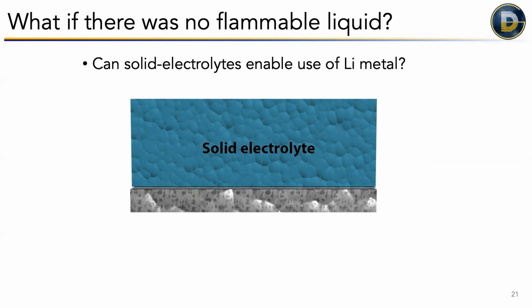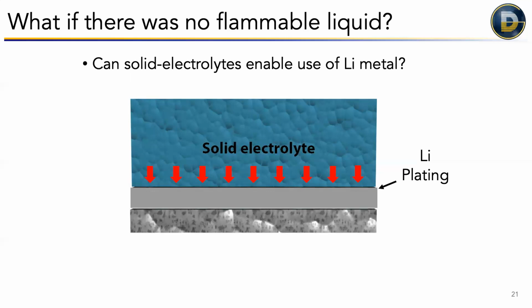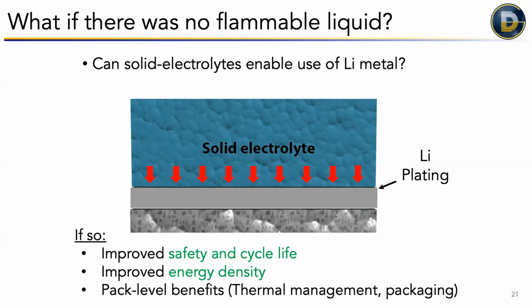But if we can use solid electrolytes to enable the safe use of lithium metal, there's a really big upside, because maybe that solid electrolyte could make the lithium metal plate out uniformly, and then you can strip it back and cycle it safely. And that would give us dramatic improvements in safety, cycle life, and big one, energy density, as well as some pack level benefits, because there's a lot of weight and space and cost that's used to control the temperature of lithium-ion batteries. Because if they get too hot, you get thermal runaway and they catch on fire and blow up, basically. But if we don't have that possibility, because the electrolyte is now safe inherently, you don't need all that thermal management and packaging stuff, and you can make a big improvement.